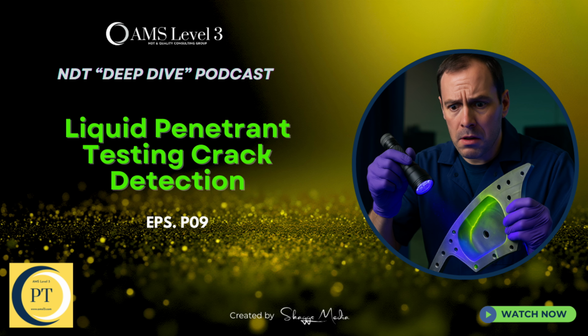So the test itself could inadvertently cause a future failure mode. Potentially, yes, if the wrong chemistry is used. That's why, for these critical applications, it's mandatory to use special low-sulfur and low-halogen penetrant materials where the levels of these harmful elements are strictly controlled to near zero. Wow. Another layer of control needed based on the material.